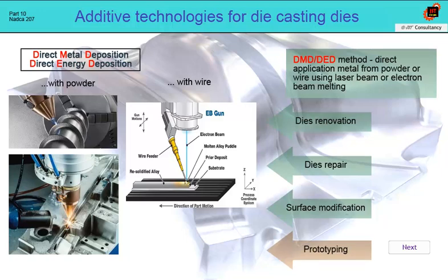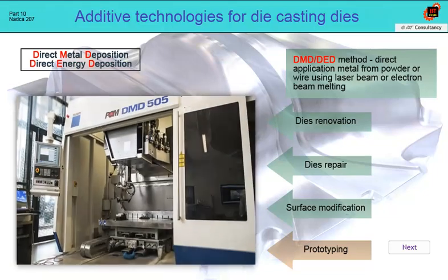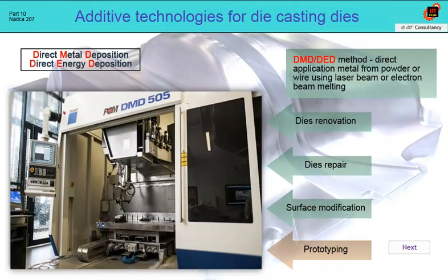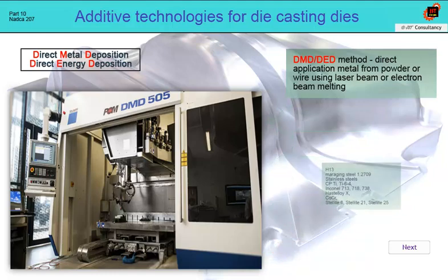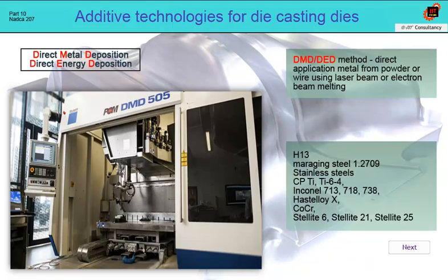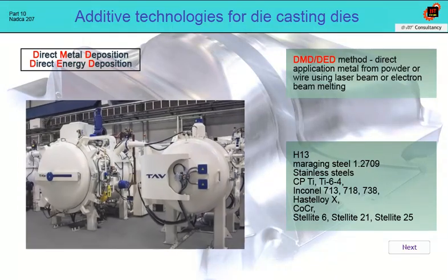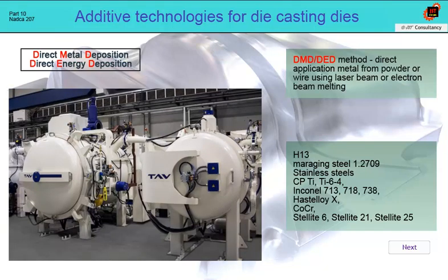For example, this device for DMD technology is a portal version with a table size of 1000 by 600 millimeters. The entire range of powder materials can be successfully applied, from powder steel type H13 through maraging steel 1.2709, various stainless steels to superalloys based on titanium, chrome, or nickel. However, it is necessary to take into account that, even in this case, printing must be followed by some heat treatment procedures, especially annealing to remove stress. This is also why access to the same size equipment for heat treatment must be ensured.